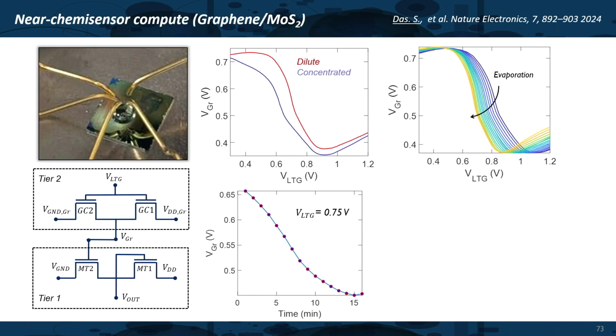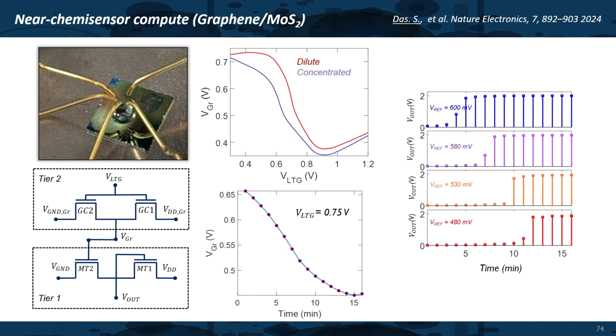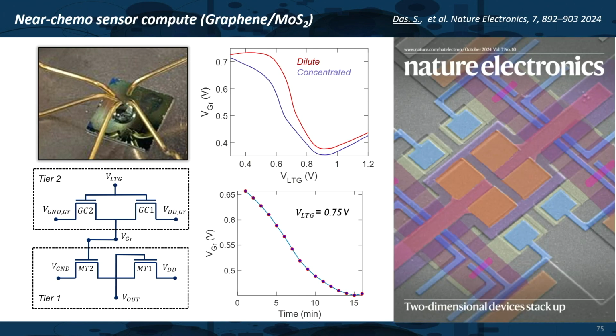With this chip, we did a very quick demonstration. We put a liquid droplet, and as the droplet evaporates, the concentration of salt in that droplet changes. That changes the response of the graphene device in an analog manner, and then we took that analog information and digitized it using some MoS2 based comparator circuit. So very simple application, but you can see the potential of integrating heterogeneous material now in this 3D stack. So that was another example. This also I think we just published 2 months back.